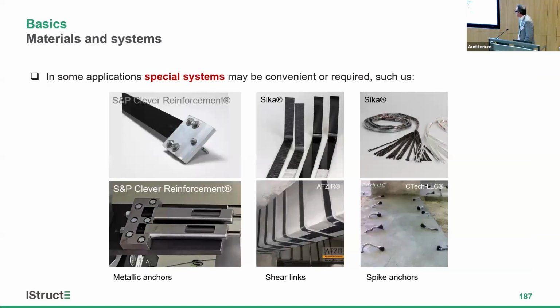In some special applications or in some special uses, we have special systems that are convenient or sometimes they are required. Here you can see some examples from the market. For instance, these ones here are normally used when we use pre-stressed FRP systems. Here, for instance, for improving the shear capacity or even avoiding as much as possible debonding at the end. And for instance, these spiked anchors that also are used to improve the bond or avoid the delamination as much as possible.